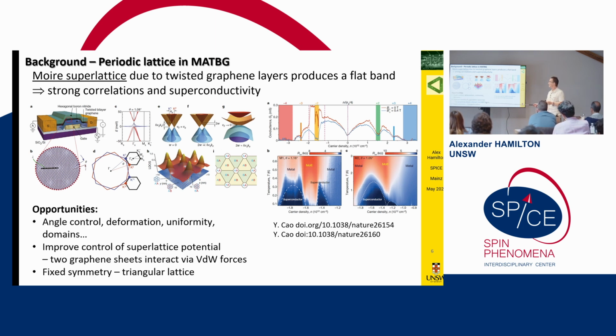There are some opportunities here in that when you're twisting these materials, getting uniform twist angle and not having twist angle disorder is slightly non-trivial. Particularly for magic angle, you have to keep the twist angle very uniform. And tuning the potential that you're creating is not so easy, because that's really set by the two sheets that you're twisting with respect to each other. And of course, you've got a fixed symmetry. You're stuck with a triangular lattice because you're starting with triangular lattice materials.